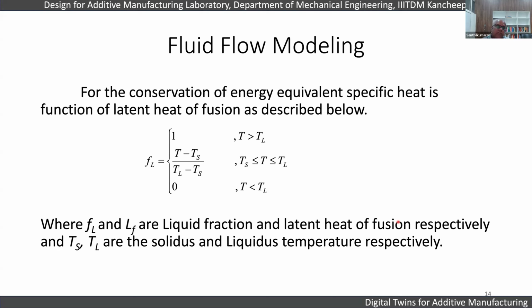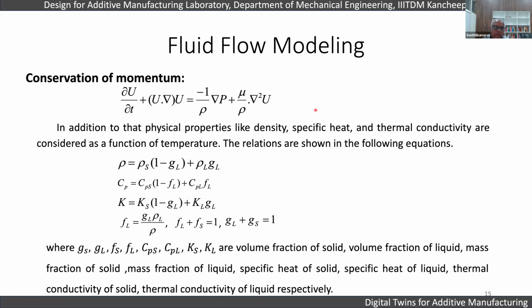But here we also have to use properties which vary with respect to temperature. So we need to take the material property as a function of temperature, and then it becomes an implicit modeling scheme. And we solve the conservation of momentum equation. In addition to that, we also give the volume fraction for density. Here you can see the density, specific heat capacity, and also the fluid fraction, the liquid fraction. All of them are calculated based on the mass fraction of the liquid, from the mass fraction of the solid, right? So the volume fraction of the liquid.